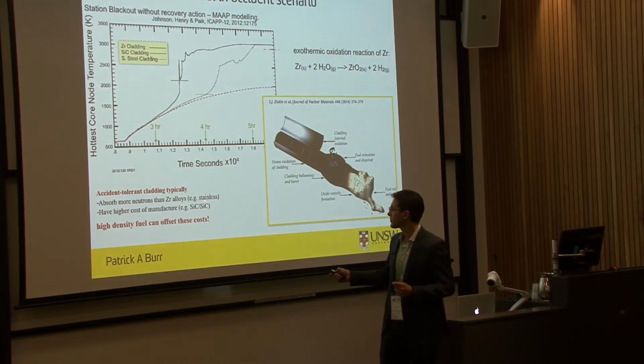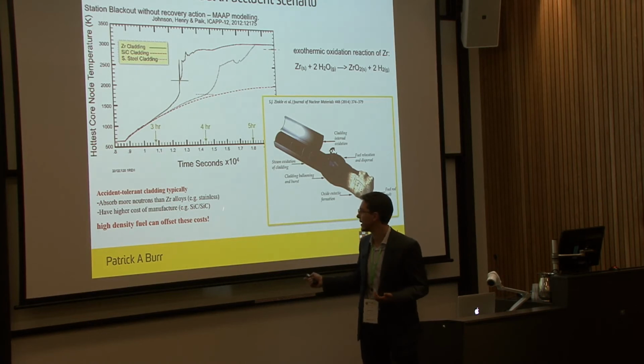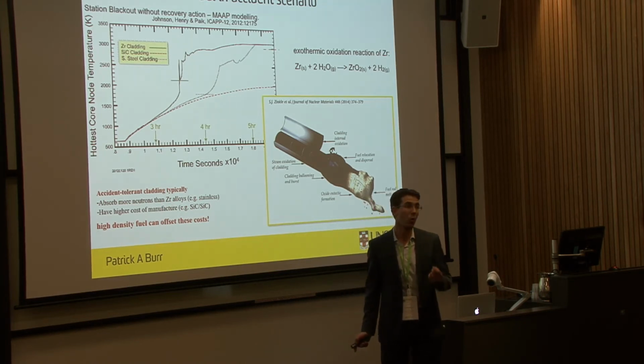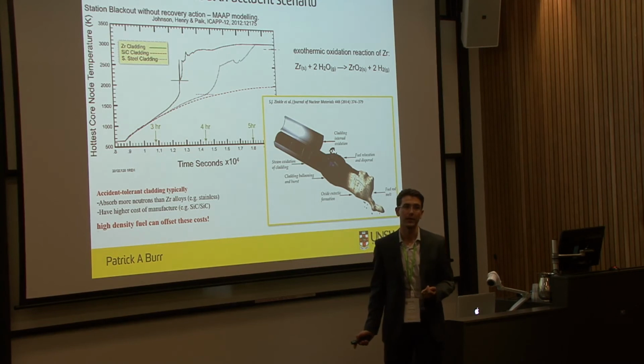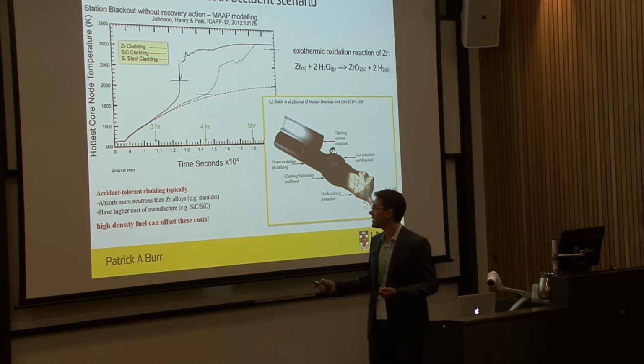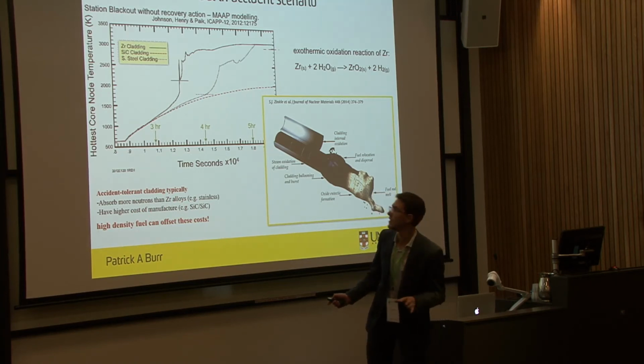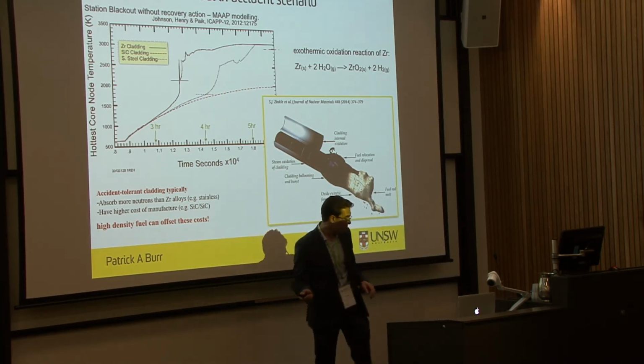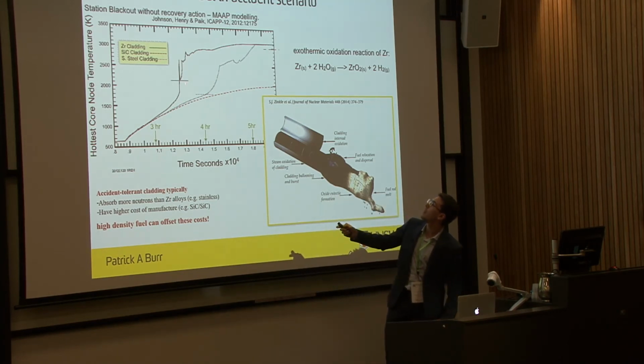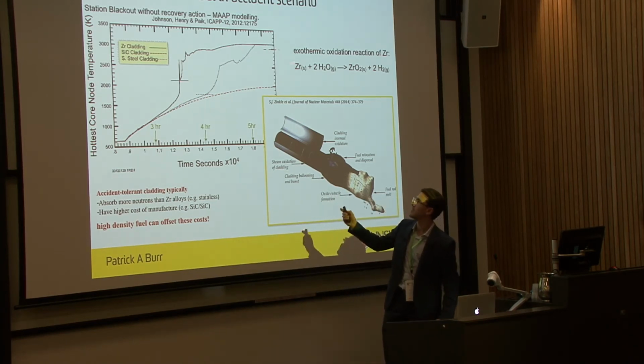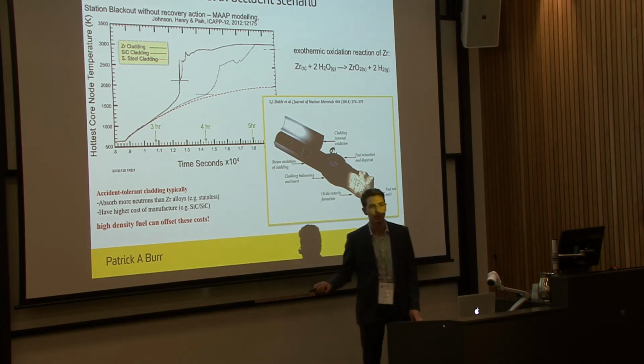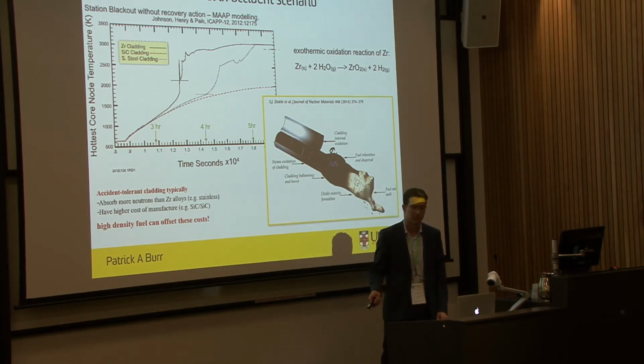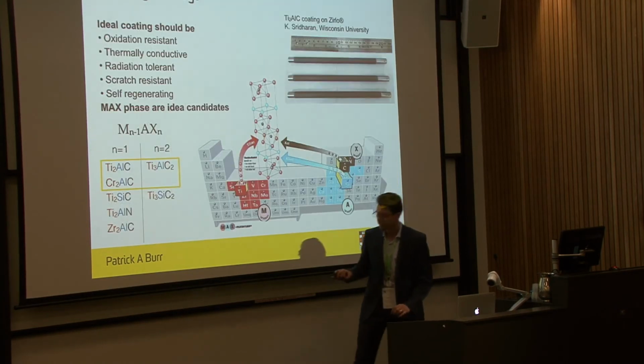Unfortunately, a lot of alternative claddings, like stainless steel, absorb more neutrons than zirconium, or cost a lot more to make, like silicon carbide. So that can be somehow countered by just simply using higher density fuel. And I'll explain that later in greater detail. However, there's one more option here that I haven't mentioned. Apart from zirconium, stainless steel, silicon carbide, and a few others, there's an approach of keeping on using zirconium, which is a very mature technology. We know how it works. But simply coating the outside of it with something that is oxidation resistant.